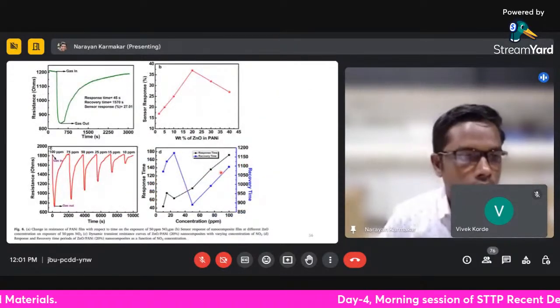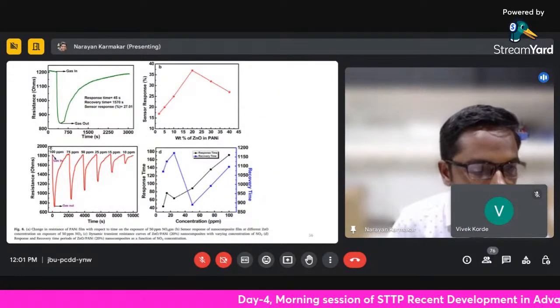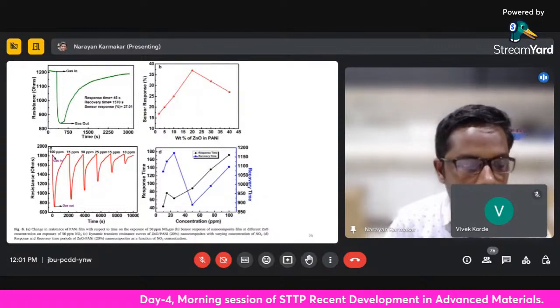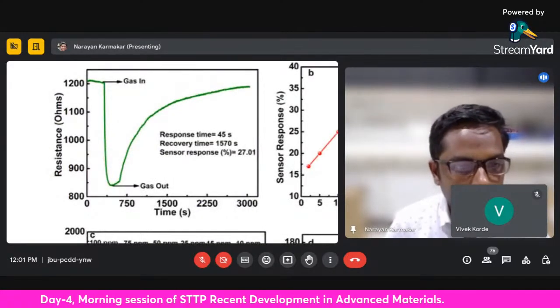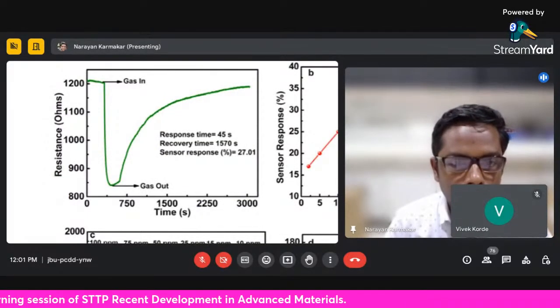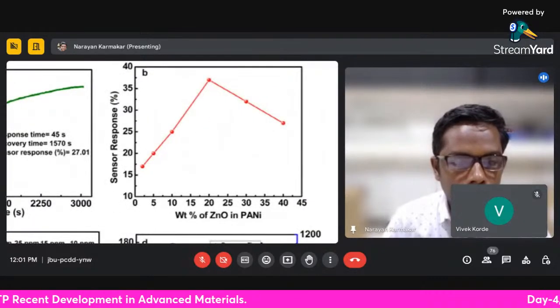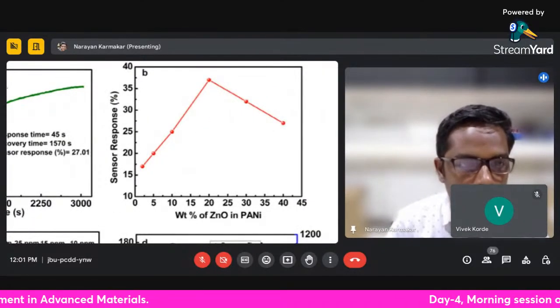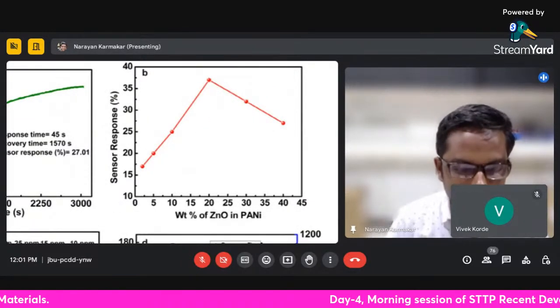Now look at this next graph: this is the response of the PANI films in the presence of NO2 gas. After that, when we doped with the zinc oxide, the maximum response was about 20%, which was observed here.